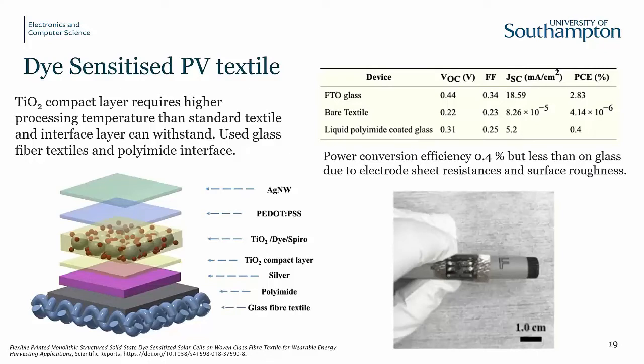Here, well, we had to cheat, really. We couldn't get down to 150 degrees processing temperatures, so we were processing over 300 degrees, so we had to cheat and use a glass fibre textile, and we had to change the interface layer to a liquid polyimide. But if you do all this, it functioned. We achieved efficiencies of about 0.4% with the dye-sensitized, and the flexibility is pretty reasonable.